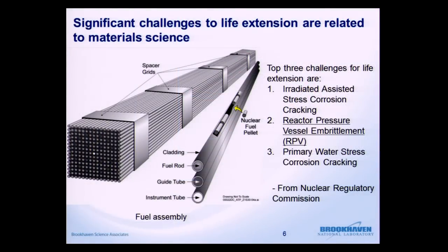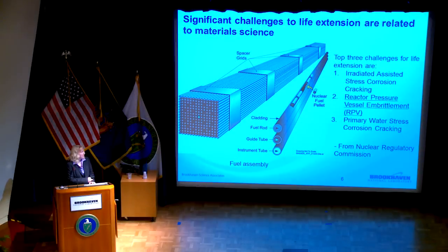So significant challenges to life extension are related to material science. This shows a fuel assembly from a core. The fuel is located in small fuel pellets, the uranium dioxide, and these pellets are located in a fuel rod, which is clad, which is known as cladding. So currently the cladding is zirconium alloys, but there's also efforts to replace the cladding with advanced materials and advanced steels. According to the Nuclear Regulatory Commission, the top 3 challenges for life extension are irradiation-assisted stress corrosion cracking, reactor pressure vessel embrittlement, and primary water stress corrosion cracking.